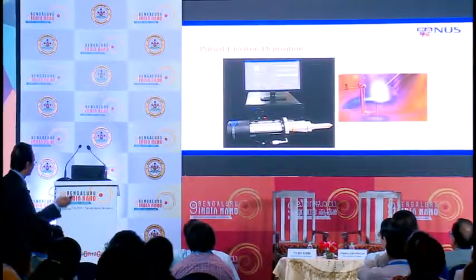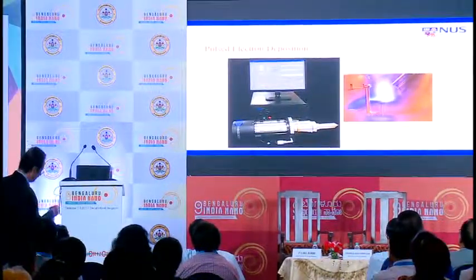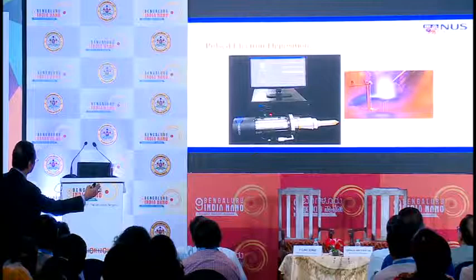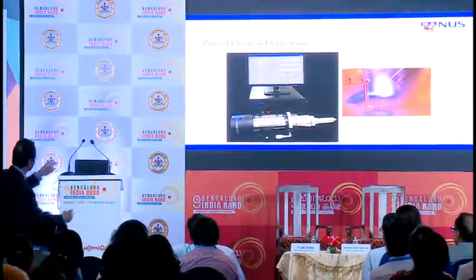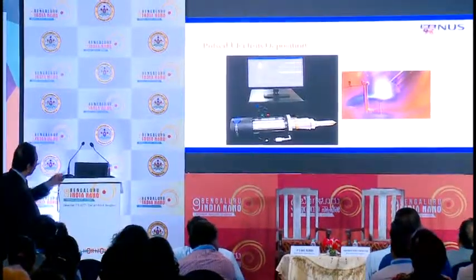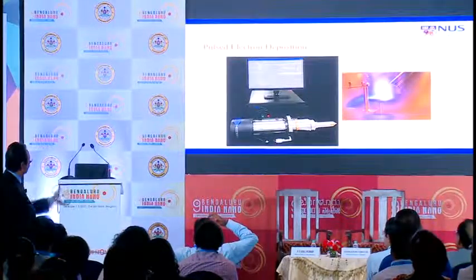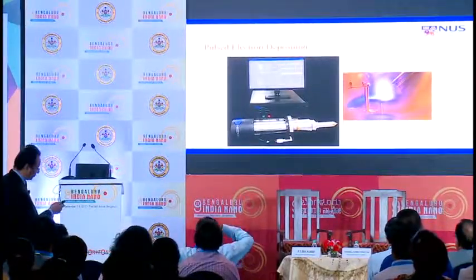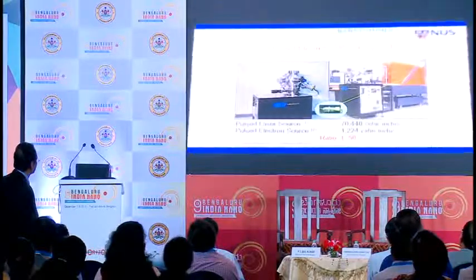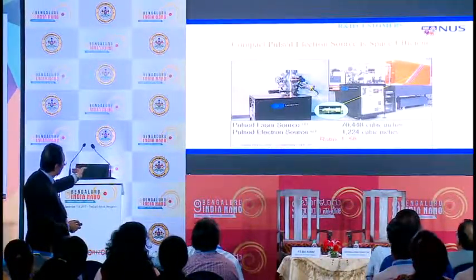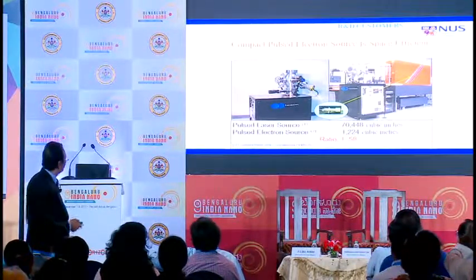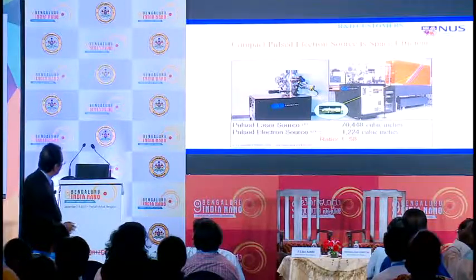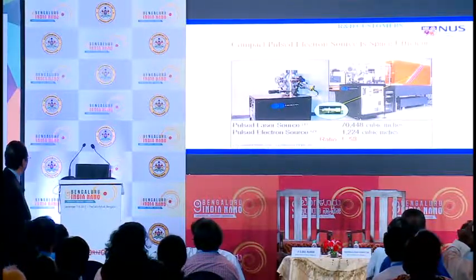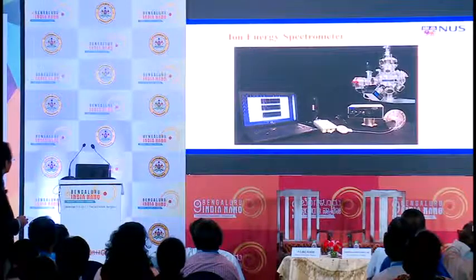Now, there's another invention that we have, called pulsed electron deposition, where the laser, which is a very big object, can be replaced with something really small, roughly a foot and a half in size, this pulsed electron source. And this electron beam, being hit on the target, also generates a very beautiful plume, and you can use this to deposit film. Here is the size comparison. You see the PED system on the left looks like this. The laser looks much bigger. So the laser is replaced by something which is roughly 1 over 58 times its size. This is one of the recent advancements.